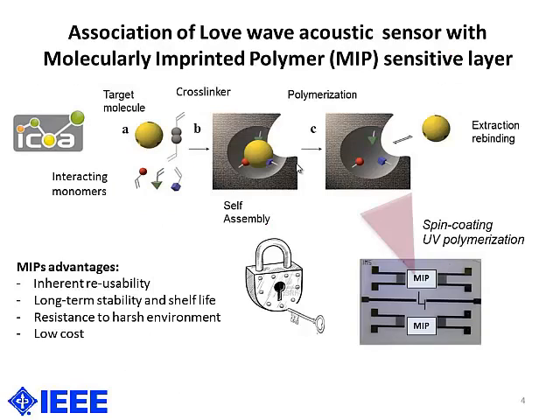these sensors. In fact, the MIP, the molecularly imprinted polymer, acts on a key and lock principle, with the extraction and rebinding of the target molecule that we want to detect. This MIP is polymerized with self-assembly from a mixture containing, of course, the target molecule and also a porogenous solvent to create some pores, and some initiators and monomers to construct this polymer around.